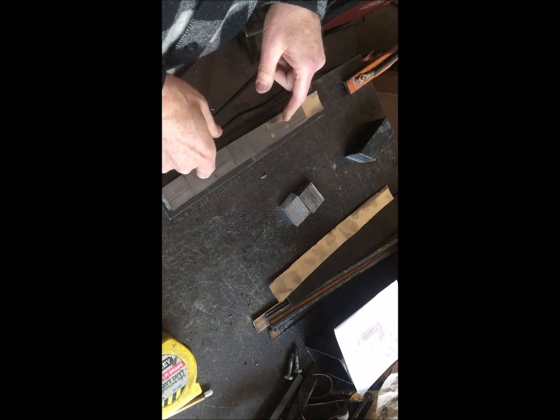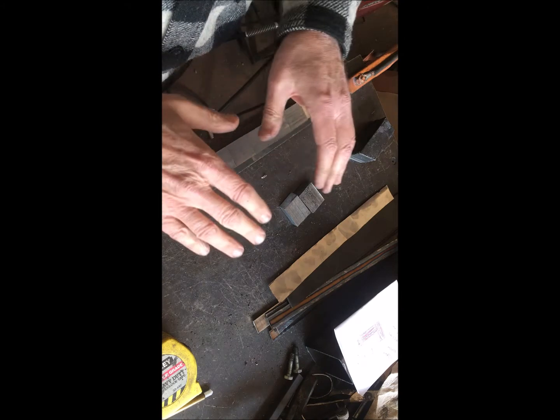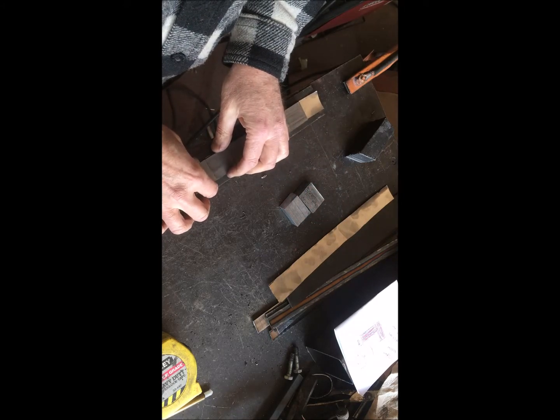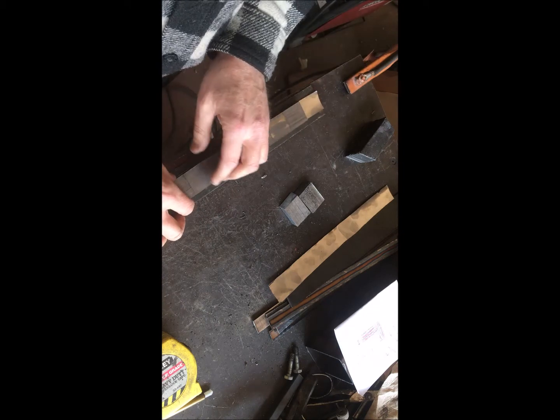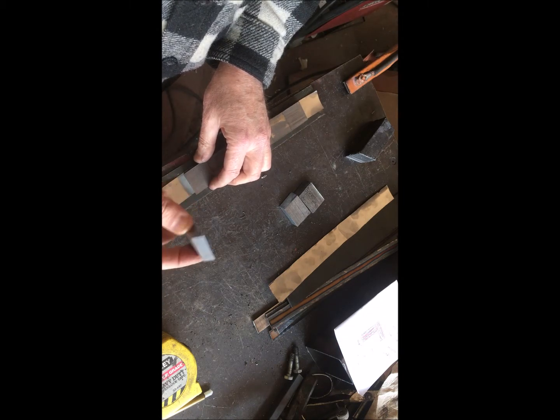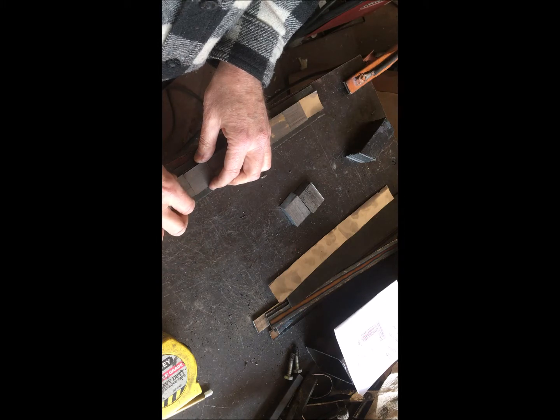The reason why we use heat is just to not have to machine everything down to a 1/10,000th and polish it in order to make it weld. The heat allows all this sort of miniature mountain range of irregularities to squish down into each other and cohere. And as long as you have nothing in between them to stop them, no oxidation, no dirt or anything like that, they will weld. So that's why it's really good to box a weld like this. It really keeps everything clean and in position. So that's the secret right there.